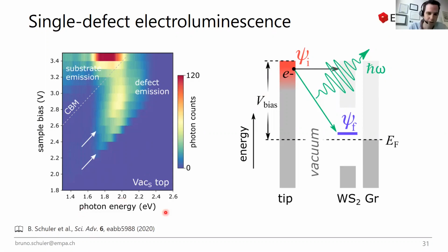So if you look now at the photon energy that is emitted as a function of the applied sample bias, we see a few things. First of all, we see a clear emission onset at a certain energy, which scales linearly as a function of the applied bias. And there are two of these onsets, which we assign to the two defect states of this vacancy in this case. So this depends on what kind of defect states you're probing. But there is quite a broad emission, which people would normally describe as a plasmonic type of emission. So fairly broad emission, but still we are just looking at a single defect.